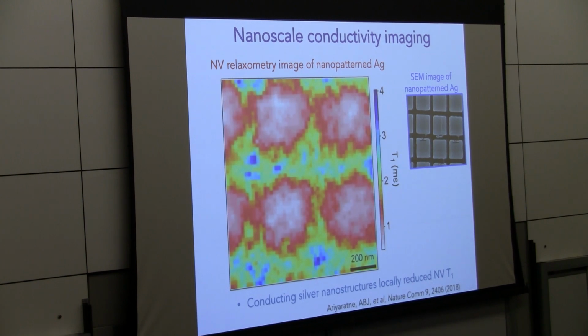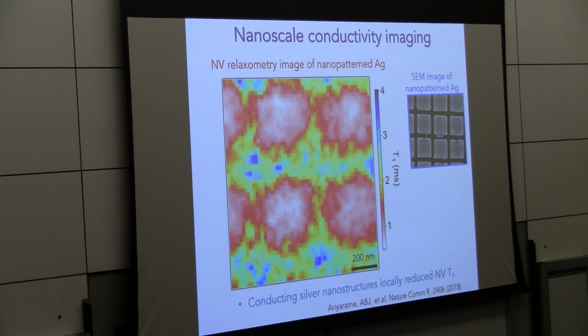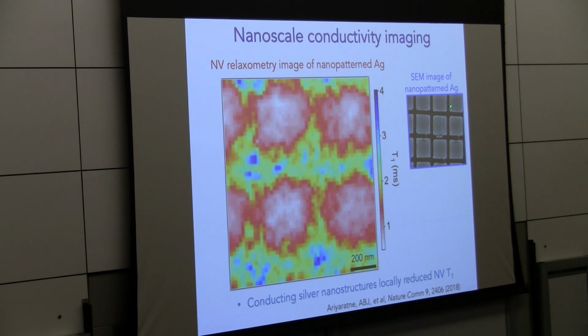Then we could do this measurement at every point in a scan to image this local conductivity. So here we took a nano-patterned silver film, an 80 nanometer thick silver film, and monitored the T1 of the NV center as we scan over this film. We see that when we're over one of these conducting pads, the T1 goes down. When we're between the pads, the T1 goes up. So these conducting nanostructures locally reduce the NV T1.